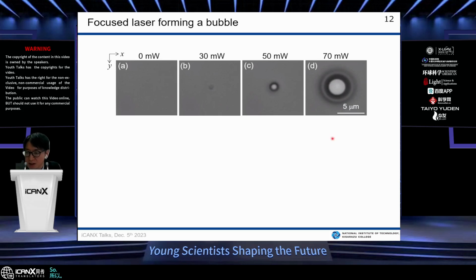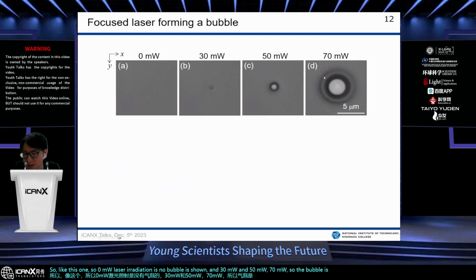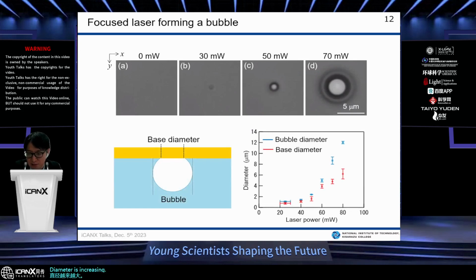So careful adjustment of illumination in the microscope provides the shadow of microbubbles. The size of the bubble depends on the intensity of laser light. Like this one, with 0 milliwatt laser irradiation no bubble is shown, and at 30, 50 and 70 milliwatt the bubble diameter increases. So like this one, the lateral axis is laser power and the vertical axis is bubble diameter.